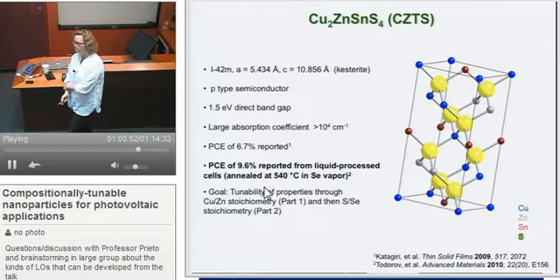The selenium goes on the sulfur site, and it essentially replaces all of the sulfur, although these films are typically not analyzed for composition after this heat treatment step. What is known is that when you heat it at that high of a temperature, you go from nanoparticles to large, microscopic grains, and those have much better transport properties.